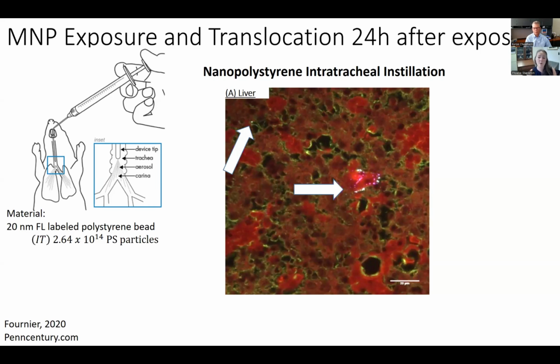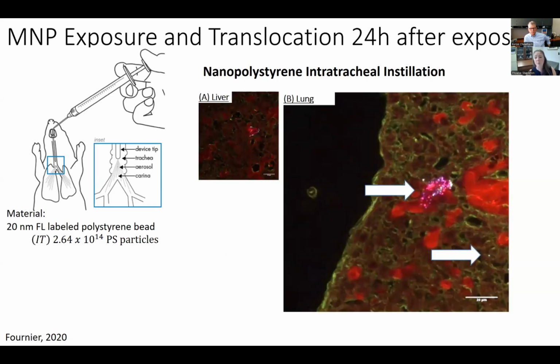We also worked with Byron and his group at CytoViva to identify these nano-sized 20 nanometer rhodamine labeled polystyrene beads in our fetal livers within 24 hours of exposure. And the white arrows are pointing those out. Not only did we find them in our fetal liver, we were able to identify them in our fetal lung. Again, these were through maternal exposures. These are still fetal tissues 24 hours after exposure.